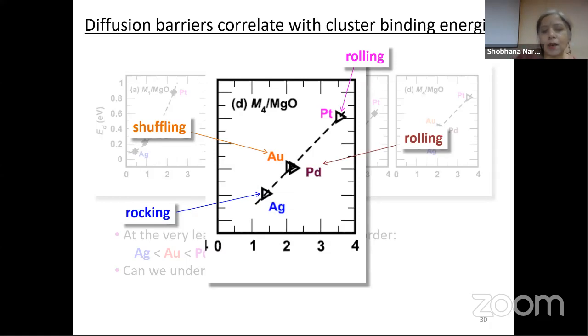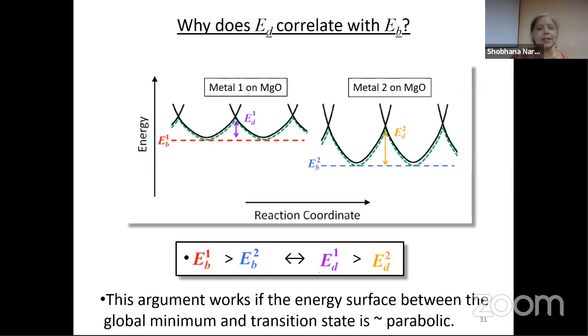For the tetramers, you have this wonderful straight line, even though the tetramers move along the surface by different mechanisms, okay? So I had shown you the platinum tetramer moves on the surface by rolling mechanism, but silver moves by a different mechanism, gold moves by yet another mechanism, and still you get this excellent correlation. Okay, so this is a sort of simple hand-waving explanation. When a cluster moves on the surface, if you can approximate its energy landscape by a superposition of parabolas.